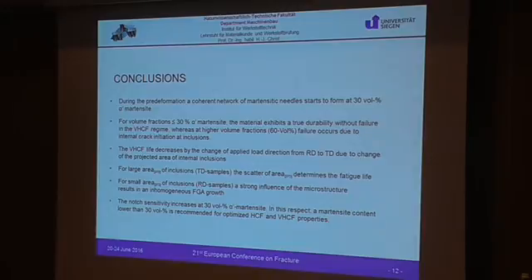For the TD samples, we could see that the dimension of the inclusion is the main parameter controlling the fatigue life, whereas for RD samples, it's not the same. In this case, the local microstructure in combination with a very low delta K results in a very inhomogeneous FGA growth, so that we cannot correlate the dimension of the inclusion with the fatigue life. The notch sensitivity test showed that for predeformed austenitic stainless steel, a martensite amount lower than 30% should be obtained in order to have optimized HCF and VHCF properties for the deformed martensitic or austenitic stainless steels.